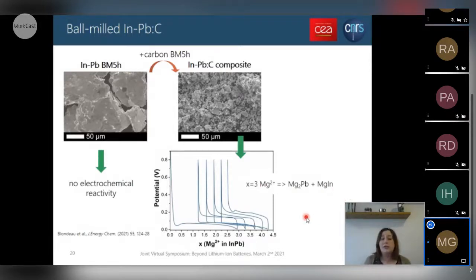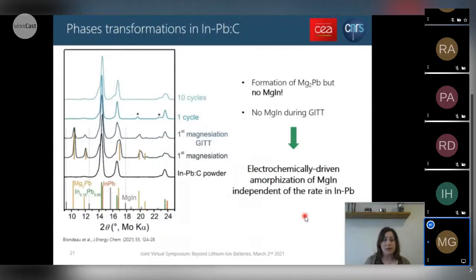Similarly, we checked the phase transformation through ex situ XRD in this InPb carbon composite. We looked at the phases formed after the first magnesiation. As expected, we see the formation of Mg2Pb here, but interestingly, again, no MgIn phase formed. When you look at the capacity we get and the electrochemical behavior, the capacity cannot be explained solely by the formation of this Mg2Pb phase. So we infer that the MgIn phase is again formed in an amorphous state.